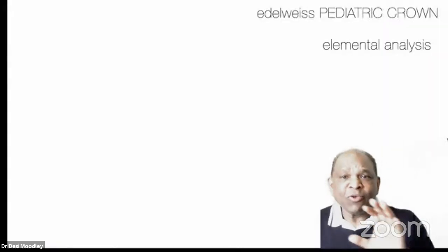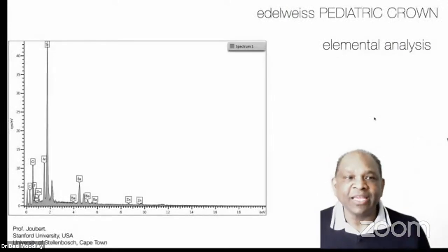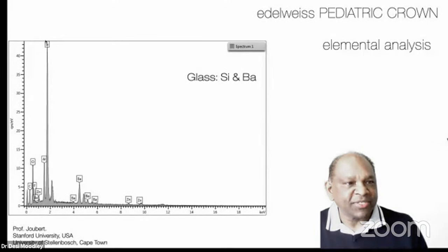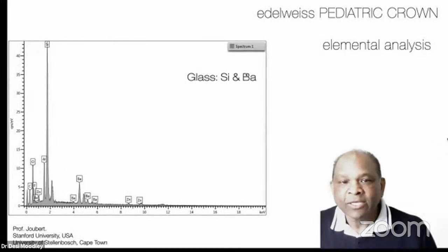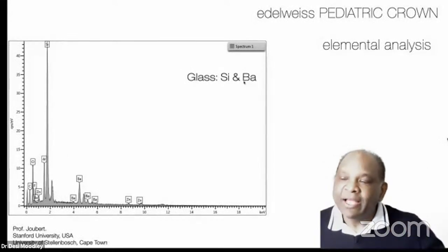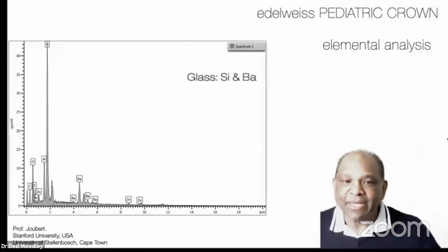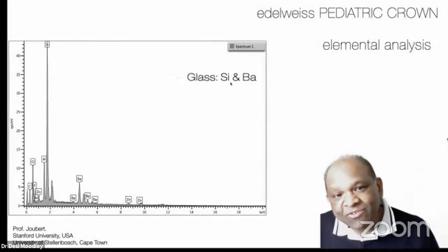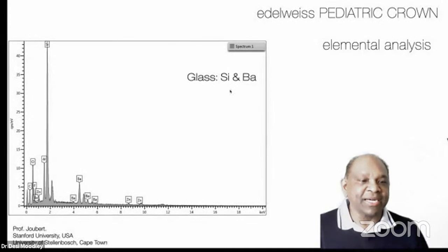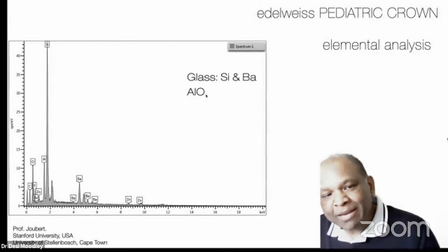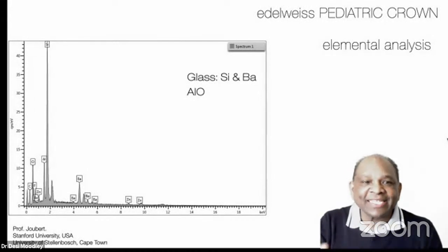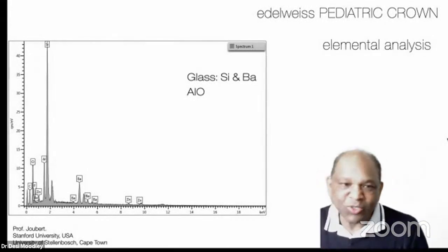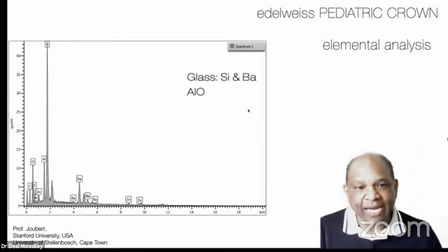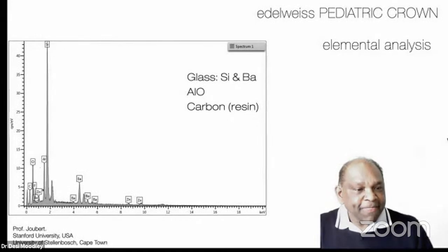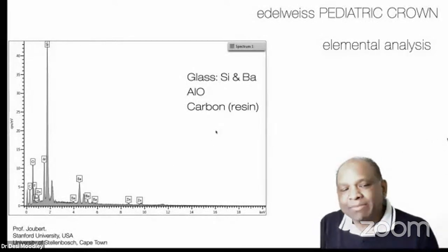So if you look at the elemental analysis of the Edelweiss pediatric crown, it consists mainly of silica and your barium glass. So that is representing your ceramic or your pure glass ceramics or your like feldspathic. So that gives you the aesthetic properties of the Edelweiss pediatric crown. Then they've included aluminum oxide, and that gives you the strength, and that has taken the strength of the material close to your particle filled ceramics. A little bit of resin is maintained here, and that's in the form of carbon there, and that is less than about 8 to 9%.